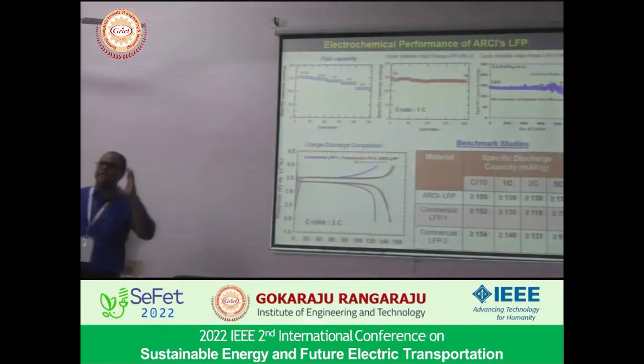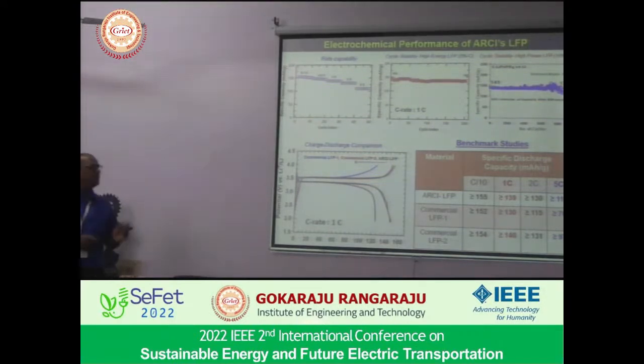Whatever we synthesized at 20 kg level, that material we tested for electrochemical performance validation, and we validated at different charge rates. 0.1 C means you are giving 10 hours for charging, 10 hours for discharge. When you give that slow charging, you get 150 milliampere hour per gram. When you are charging at 5 C you are giving only 12 minutes for charging. So even at fast charging we could get more than 100 milliampere hour per gram.